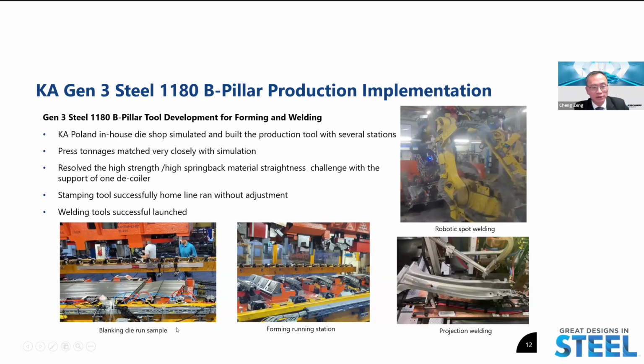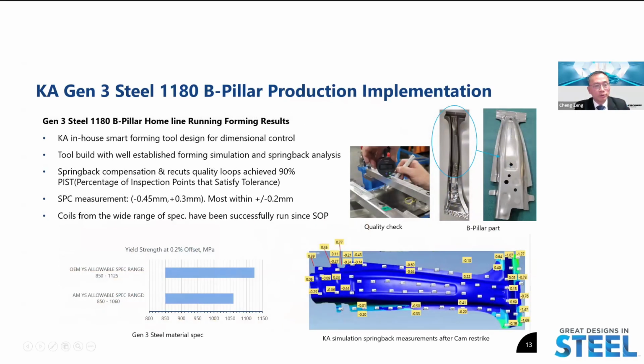You can see here these blanking die run samples, this is the forming die running samples, and this is the welding cells, as well as the spot welding and projection welding, robotic. Okay. I would like to highlight the whole line's running forming stage results. KIRCHHOFF in-house smart forming tools were designed for dimension control, and the tool was built with well-established forming simulation for high strength steel and a springback control compensation method. Through a few recuts, we achieved 90% of PIST, percentage of inspection points, that satisfy tolerance. Okay, SPC point measurements are also very nice on the whole line.